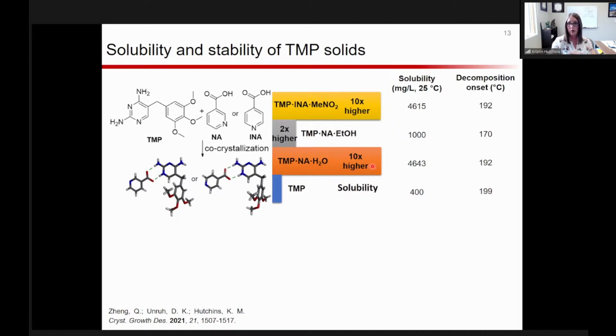It's important to look at thermal stability of these systems as well, because you typically modify the thermal behaviors when you do co-crystallization, so things like melting point or decomposition. But it's important to study that so that you don't actually change the stability significantly to the point that you couldn't store it on shelves, for example. Interestingly, in all of these cases, we saw similar decomposition temperatures when compared to trimethoprim by itself. So really not dramatically changing those properties.